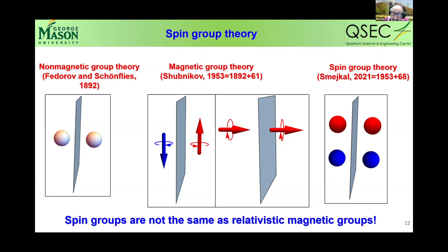For instance, one annoying issue with chromium antimonide, which is otherwise a high Néel temperature, very good metal material, is that the Néel vector, that is the direction of the chromium spins, is along the 0, 0, 1 direction. And it turns out that for this direction, no anomalous Hall effect is allowed in any geometry. In fact, the code by Andrei Smolyanyuk that I will present to you quickly later, and which will also be presented in a tutorial on altermagnetism at the next March meeting, can tell you simply based on CIF files and the magnetic pattern, whether this pattern is altermagnetic, and also whether it has anomalous Hall effect, and if it does, in what geometry.